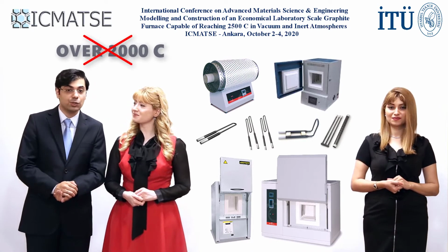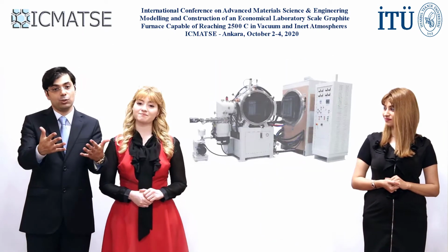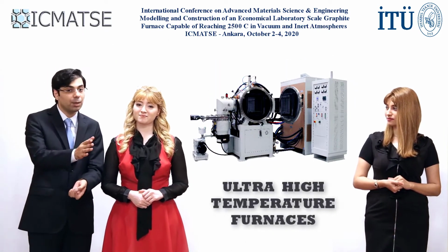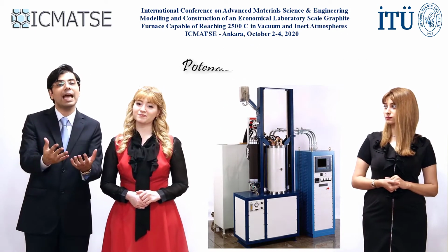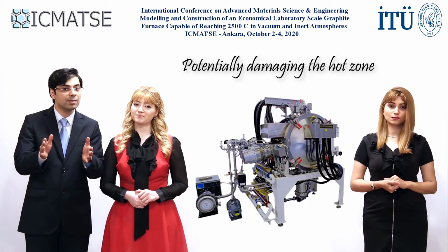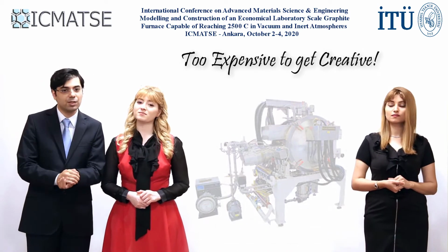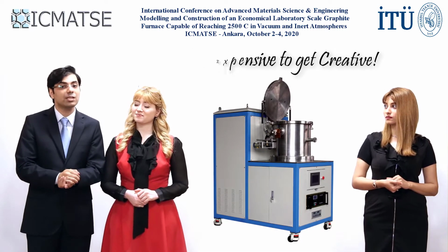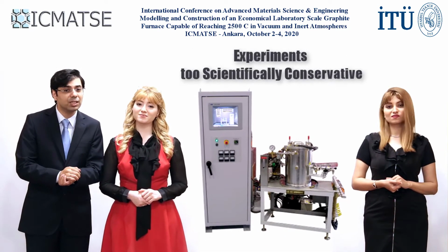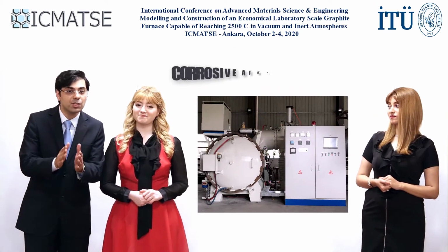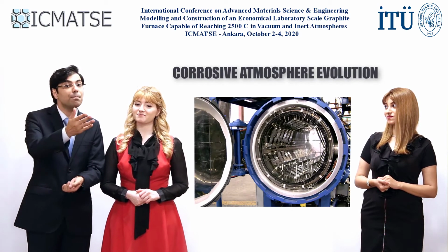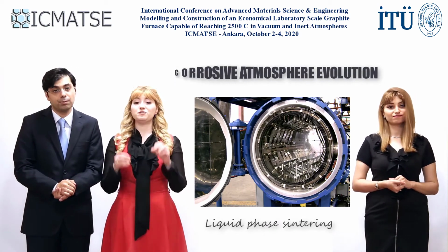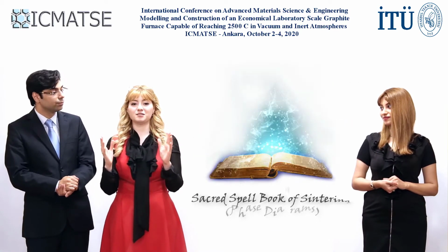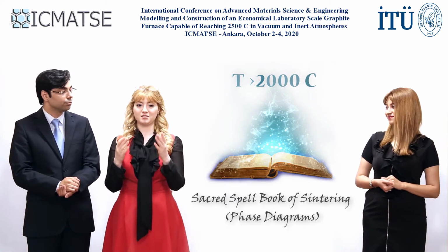It was also interesting to see that a few of our colleagues who had access to ultra-high temperature furnaces had another problem. And that was the fear of doing experiments which could potentially damage the hot zone components, simply because these equipment are just a little bit too expensive. And for that reason, experiments done with such furnaces in most labs are too scientifically conservative, and the equipment are not used at all if there is a chance of a corrosive atmosphere evolution, as is the case in many liquid phase sintering experiments.